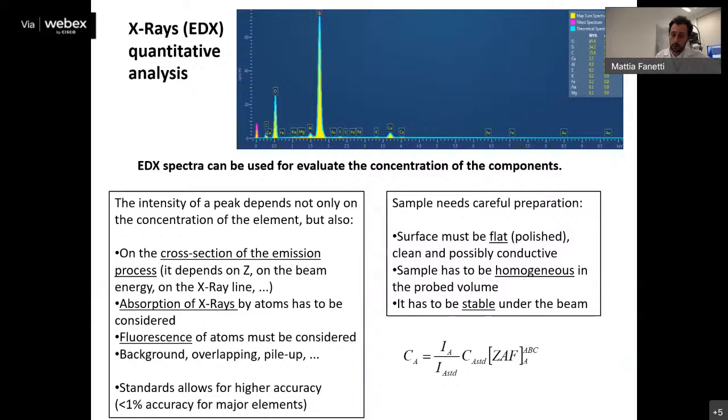But otherwise, at a given level, you cannot refine this too much unless you use much more complex software, where you can insert the structure of your sample, if you have layers, clusters, spherical clusters, nanowires, and so on. Then by running calculations, you can simulate the spectrum and compare it with your spectrum.